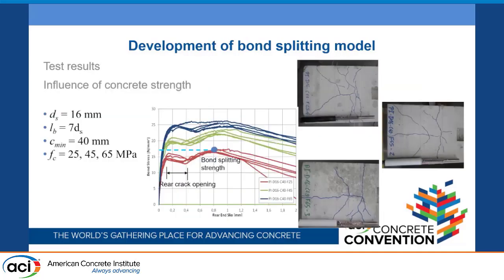So here we see some typical test results for the influence of concrete strength. So with these kind of specimen, we always reach the splitting failure of the rebar. And we can see initially the load increases, then we get, let's say, the crack coming from the back, which leads to a rear crack opening and therefore a slight drop in the load.